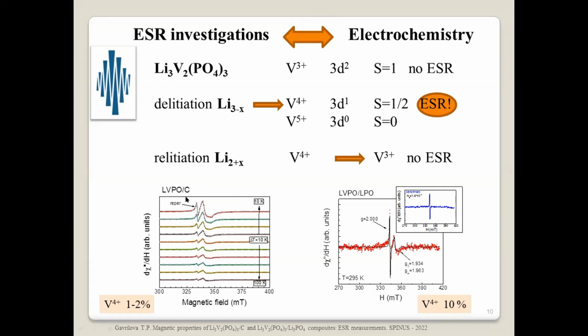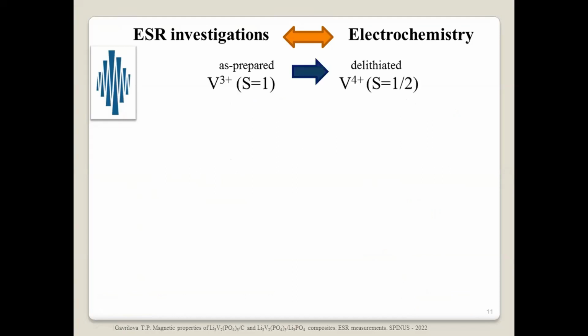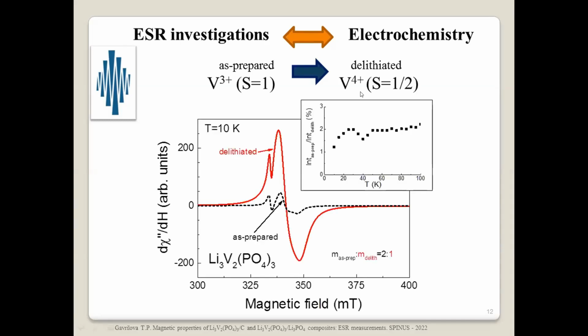In the composite with carbon, the amount of vanadium 4+ was about 1 or 2%, and in the composite with lithium phosphate, the amount of vanadium 4+ was much higher, about 10%. Then, as I have already said, during the delithiation process vanadium should change its valence state to 4+, and we really can observe very significant changes in the ESR spectrum, in the intensity of the ESR spectrum.